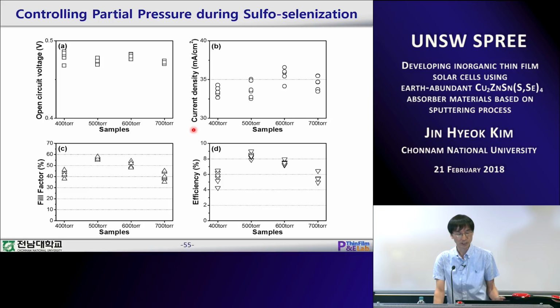The cell result shows that the sample kept at 500 torr shows the highest cell efficiency compared with the other 400, 600, and 700 torr pressurized samples. So by tuning the partial pressure during the sulfo-selenization process, we could get a better result at 500 torr.